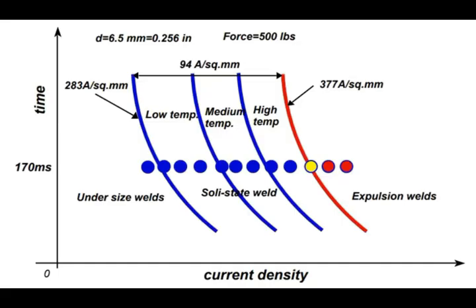This is the weld lobe built with the data from the table. The low temperature ranges from 750 degrees Celsius to 907 degrees Celsius. 907 degrees Celsius is the evaporation temperature of zinc. Medium temperature ranges from 907 degrees Celsius to 1200 degrees Celsius. At 1200 degrees Celsius you will start to have dendrite and heat affected zone. High temperature ranges from 1200 degrees C to 1500 degrees Celsius. At 1500 degrees Celsius metal starts to melt, and expulsion occurs.